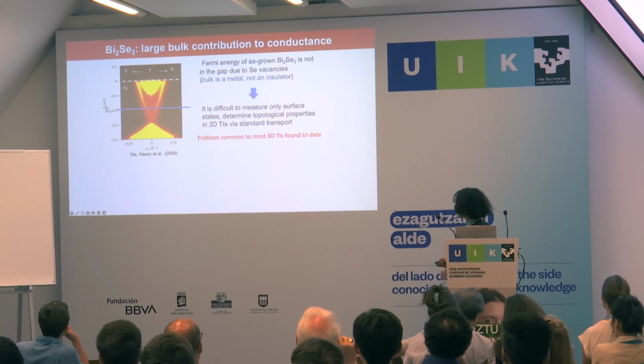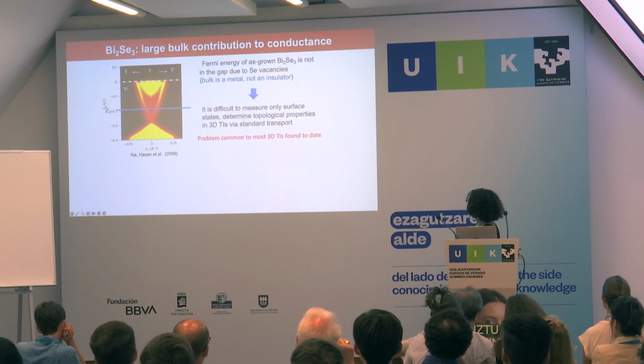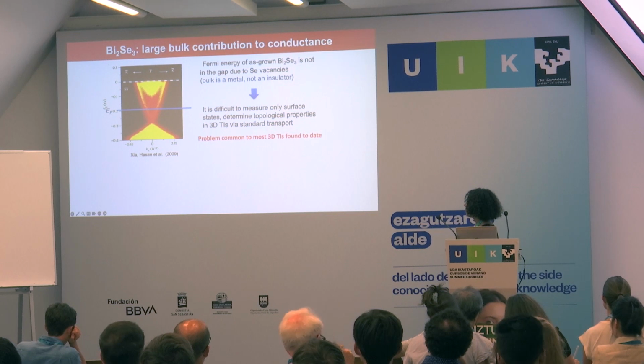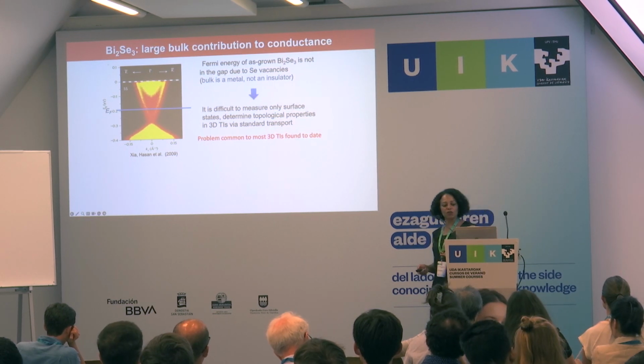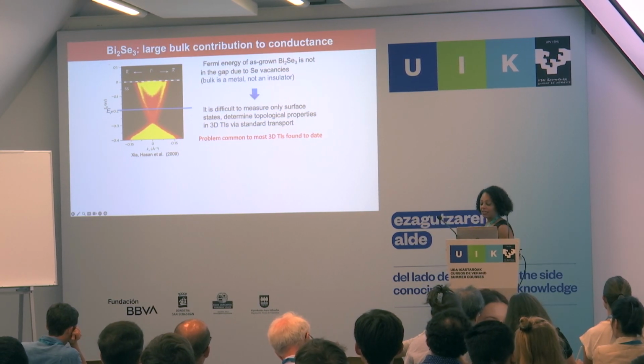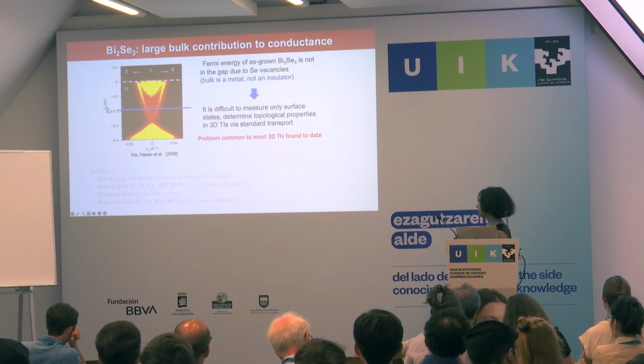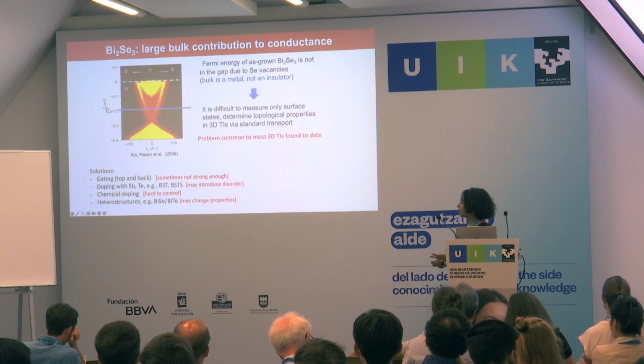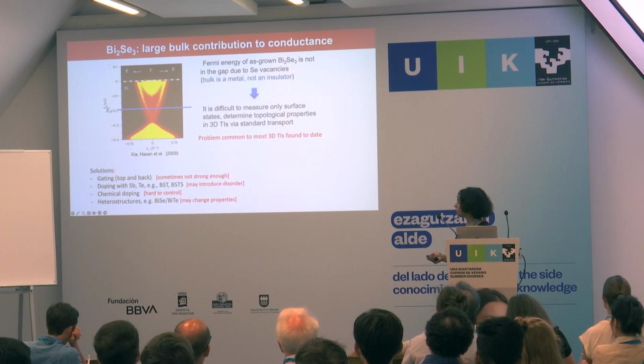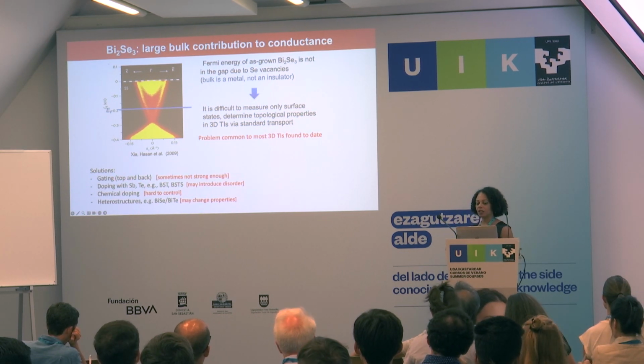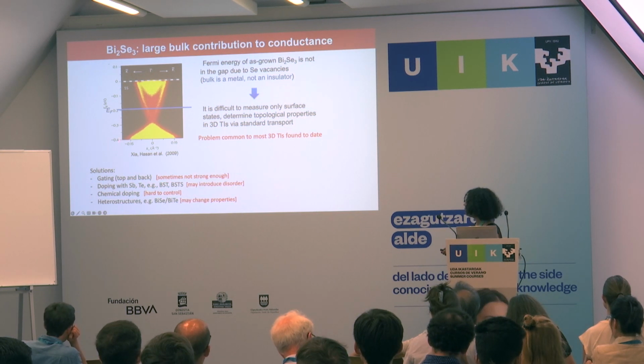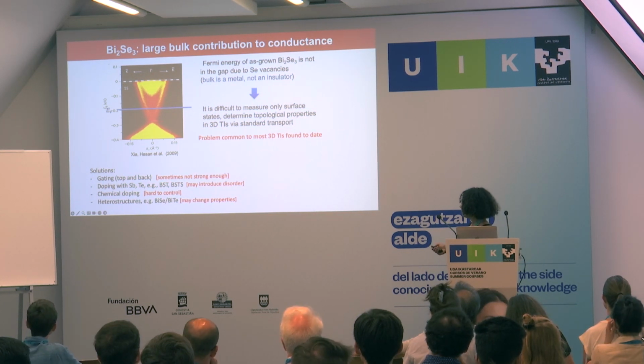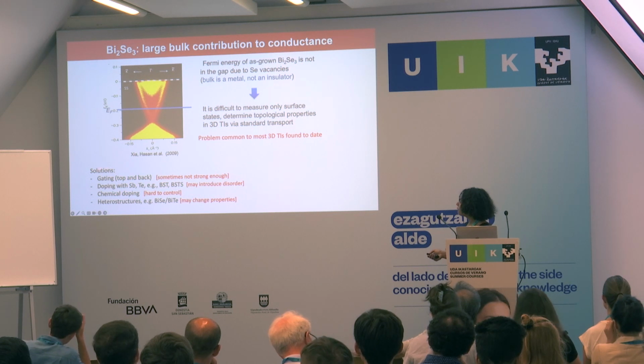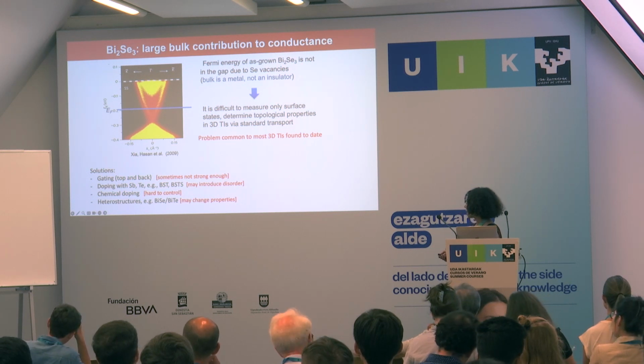Generally, like I said, almost all 3D TIs have this problem of vacancies leading to bulk metallic states. And so it's a really big issue of how do we actually attain the surface state regime in these cases. There are many different solutions for getting there. You can do gating, top gating and back gating. That's pretty effective. Sometimes using a back gate alone isn't strong enough to tune the Fermi energy into the Dirac point. There's a lot of doping that you can do, especially things like BSTS or BST.